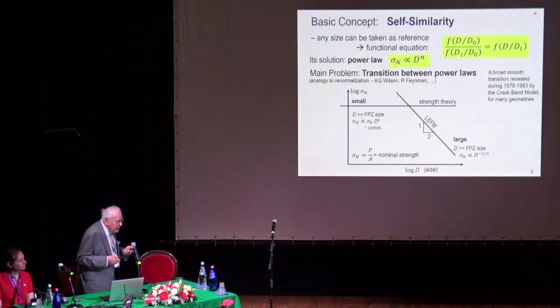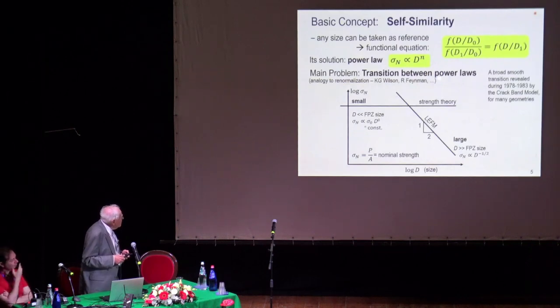Now, scaling, we should realize the problem of scaling starts with the problem of self-similarity. Self-similarity is a basic concept. It is the case where the response does not depend on the reference taken. So if any size can be taken as a reference, response must be similar, and that leads to this functional equation. F is an unknown function of size d, and some characteristic size d0, another characteristic size d1. If these two are arbitrary, one can easily show that the only solution is the power law. So power law means self-similarity, and that's why it's endemic in all problems of physics